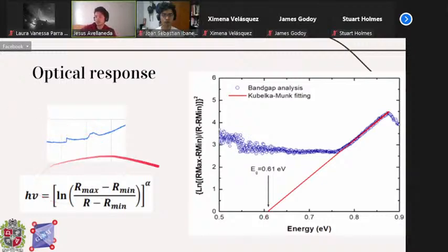We applied the Kubelka-Munk method, as you can see in the equation right here. As you know, the Kubelka-Munk method is a relationship between the energy and the reflectance values of the sample that you are analyzing. And this alpha coefficient basically tells us the type of gap that we have. If said coefficient is 2, we have a direct gap, and if it is a half, we have an indirect gap. As you can see in the graph on the right part, we found that the n necessary for a good data fit was 2.